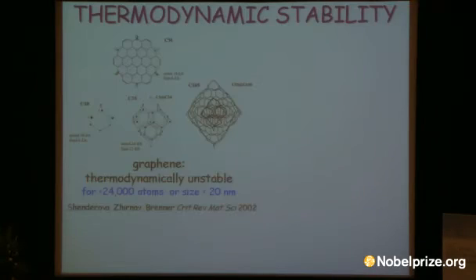Then I looked further in the literature, and specifically for carbon, it was known that a flat sheet is thermodynamically unstable until you reach sizes of the order of 20 nanometers in diameter. It's a lot of atoms together. Before that, all 3-dimensional shapes are more favorable. So the question is how to get to those large sizes without passing through intermediate growth at these smaller sizes.